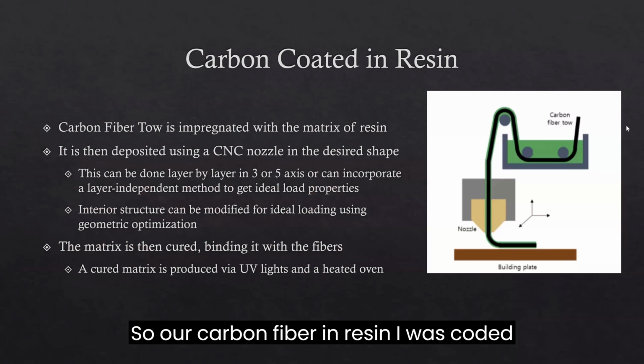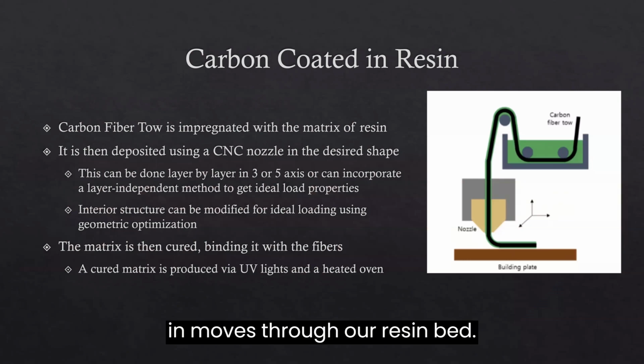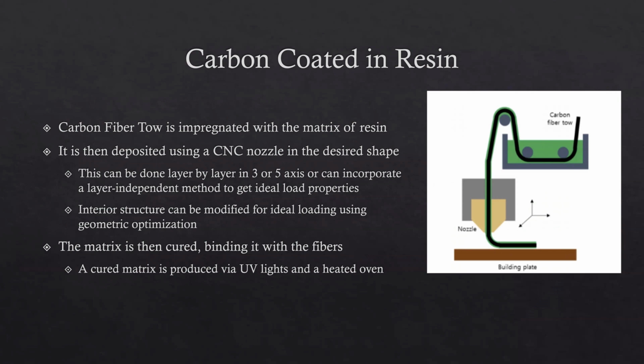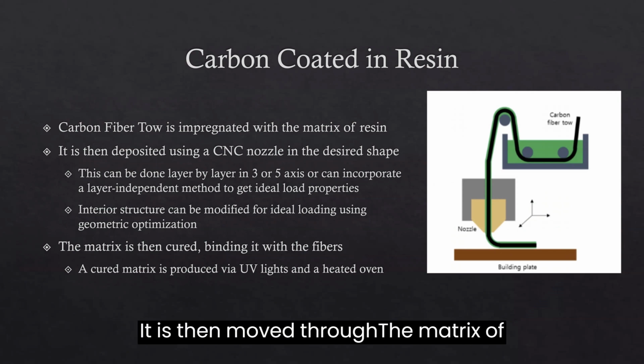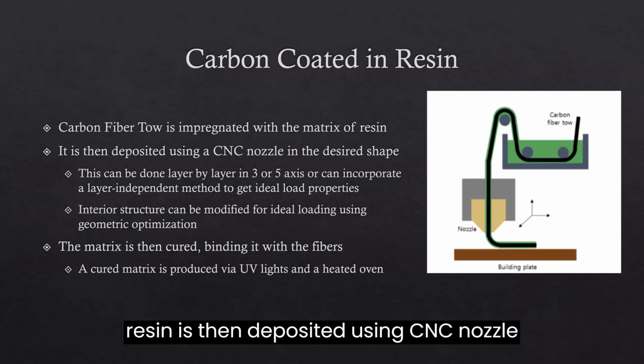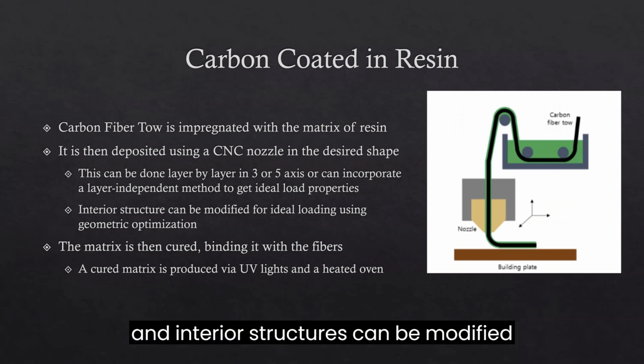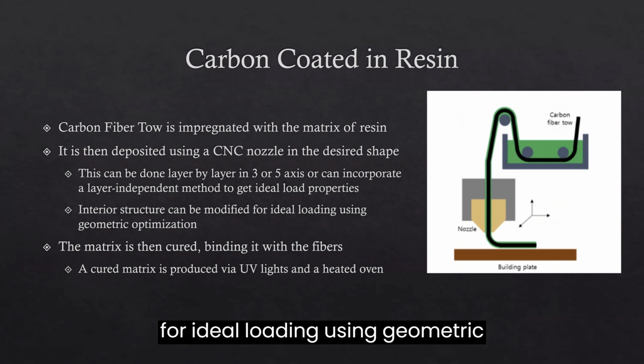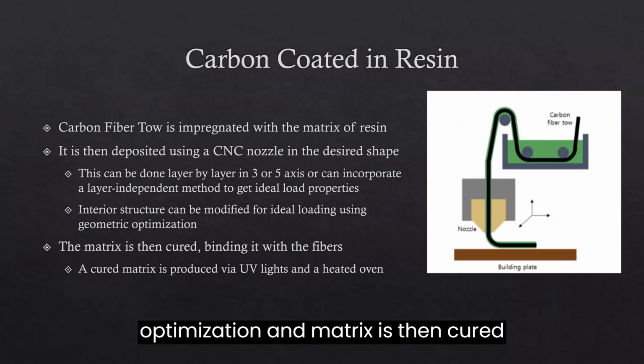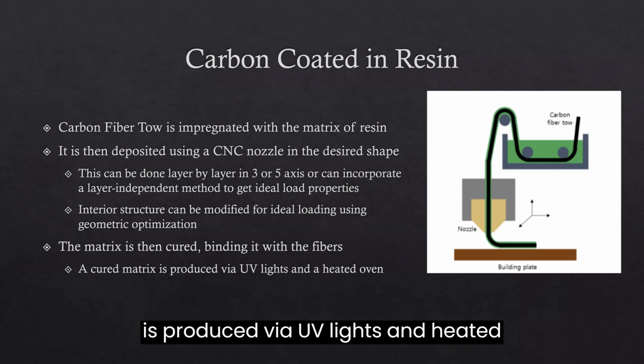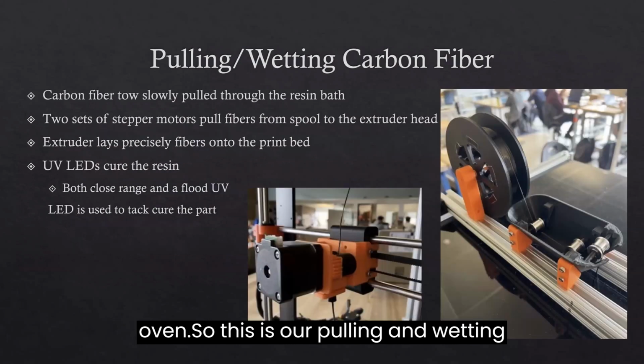So our carbon fiber in resin, how it's coated, it moves through our resin bed, and it's moved through the matrix of resin. It is then deposited using a CNC nozzle, and interior structures can be modified for ideal loading using geometric optimization. The matrix is then cured, binding it to the fibers. The cured matrix is produced via UV lights and heated oven.